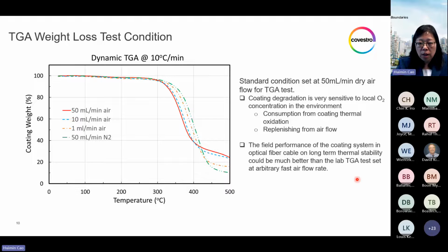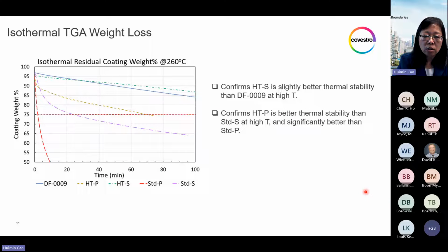But even with that expectation, you still shouldn't run the risk of using a conventional urethane acrylate-based coating for your actual application. It will still cause field stability issues, durability issues in the long term. These specially designed high temperature resistant coatings are highly desirable. It's just to show that whatever we predicted in the lab test is not to be interpreted as an absolute value, but in a relative ranking sense.